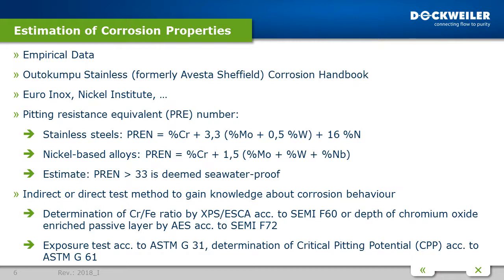Direct test methods are easier to perform. One very easy test is the exposure test according to ASTM G31 for general corrosion — you place a sample outside, wait one, three, or five years, and then assess its corrosion resistance. The salt spray test according to ASTM B117 or ISO 9227 is another direct method for pitting corrosion. A procedure giving one number with less time is the determination of the critical pitting temperature (CPT) according to ASTM G150, and the determination of the critical pitting potential (CPP) according to ASTM G61.